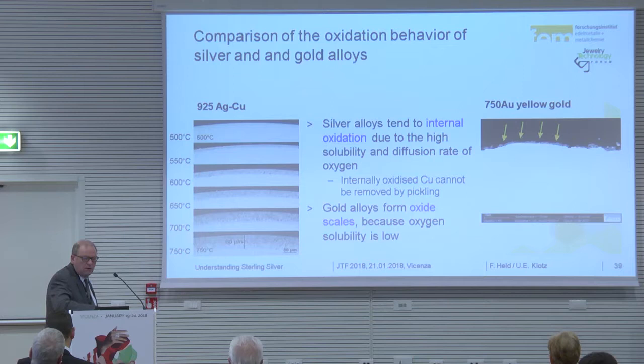Comparison of oxidation behavior of silver and gold alloys, we have seen this, so we know if we make annealing of silver under oxygen atmosphere, we get this fire stain thickness. If we make the same with 750 yellow gold, we only see a small layer of oxidation, and this is copper oxide which is on the top surface. But normally there is no inside oxidation after annealing.